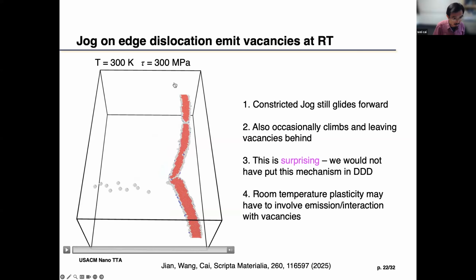You have an edge dislocation with a pair of jogs, and there's no problem for the jog to just glide in the x direction. It's a purely conservative motion. There's no need to climb. In fact, if they climb, they will need to move along the dislocation line. There's no need to do that because we didn't apply stress to force it to climb. And if it does that, then you'll have to either emit vacancies or interstitials. We didn't apply stress for it to do that.